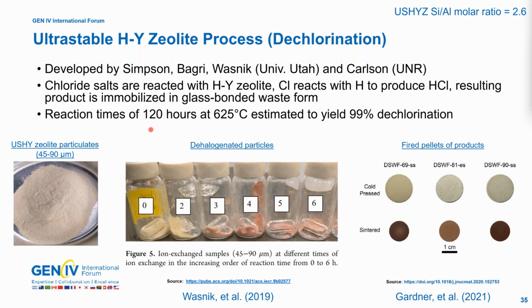This process was developed at the University of Utah by Mike Simpson. This is Manish Wasnik and then Krista Carlson. And they estimated that 120 hours would be required at 625 degrees in order to yield a 99% dechlorination efficiency. So this is a long time to run this, but when Levi Gardner was doing these tests on these different pellets, he was trying to figure out, does it have to be fully dechlorinated? So that's what these different numbers represent, the dechlorination percentage. And the materials worked pretty well. The durabilities were pretty comparable to the glass bonded sodalite.